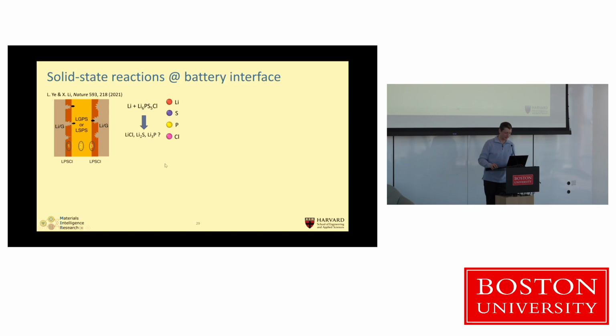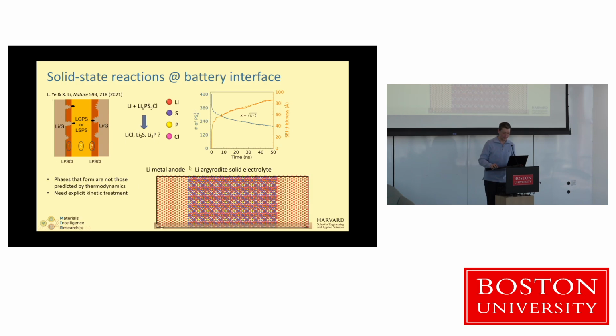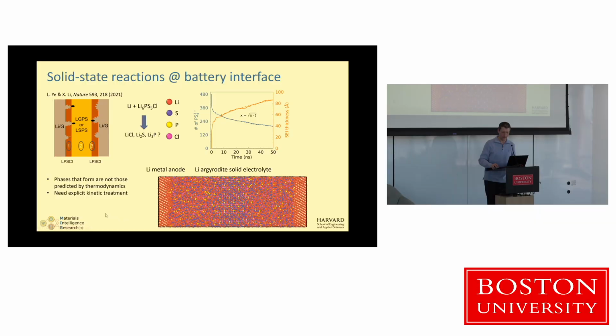Okay, so I did want to include an example of batteries, just because this previous talk was on batteries, so I put in a couple of slides here on interfaces that are responsible for degradation in solid-state batteries, or in any battery. Actually, you have these certain phases that grow in when electrodes and electrolytes meet and try to live together. They actually react over time. Some reactions are very fast. So this is an example of a simulation of a degradation reaction in a solid-state battery that has a very fast electrolyte, very fast ion conductor, a solid-state sulfide, and lithium metal, which is one of the good candidates for the electrodes. And you can see in the simulation, again, this is a molecular dynamics simulation trained on DFT data.